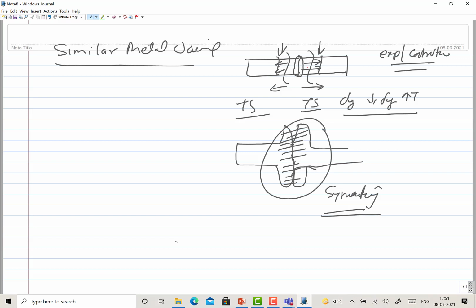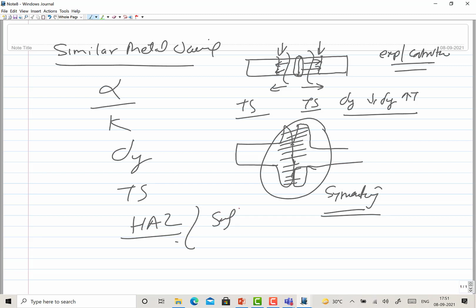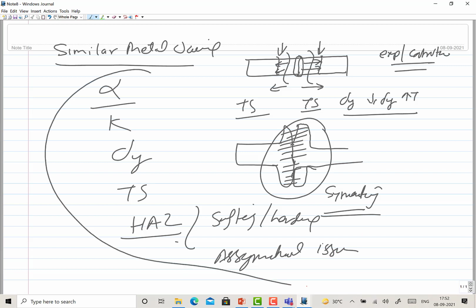But in dissimilar metal joining, all things are different. You know, alpha is different, K is different, yield strength is different, thermal softening is different, and that is why you are finding varying HAZ, somewhere softening and somewhere hardening is taking place, right? And somewhere more upsetting, other side less upsetting. So you are having an asymmetrical weld. So all those are the issues, even in case of friction welding, you come across all these problems apart from the metallurgical issues at the interface. Okay, so on the dissimilar part I will talk a little later.